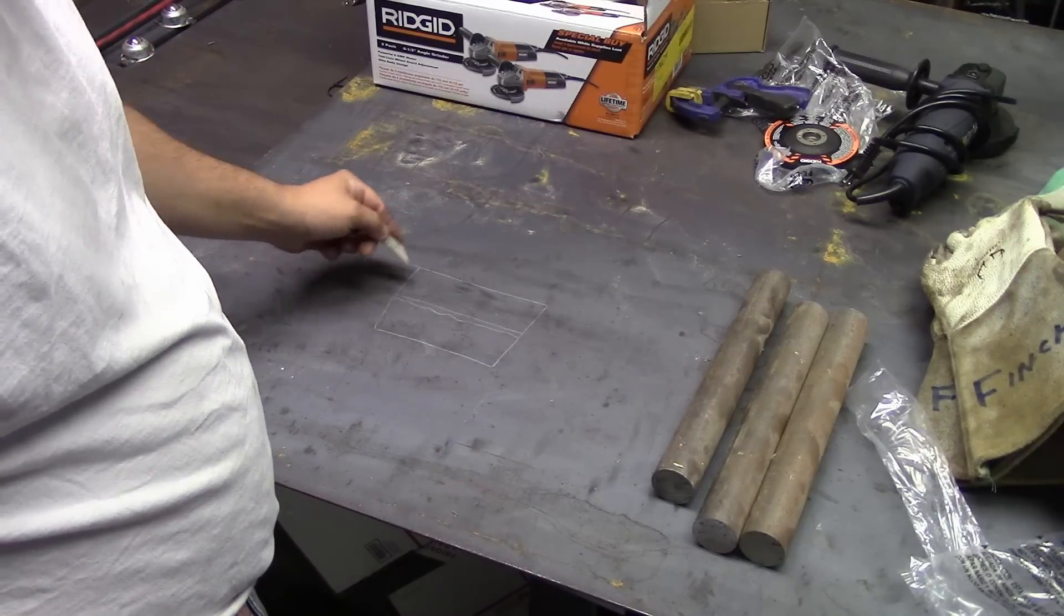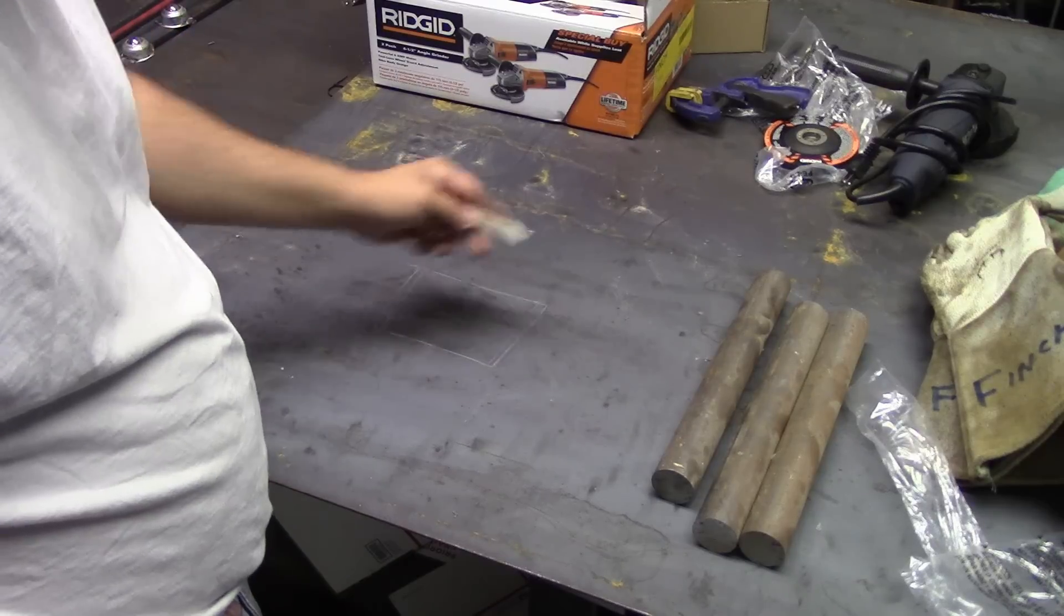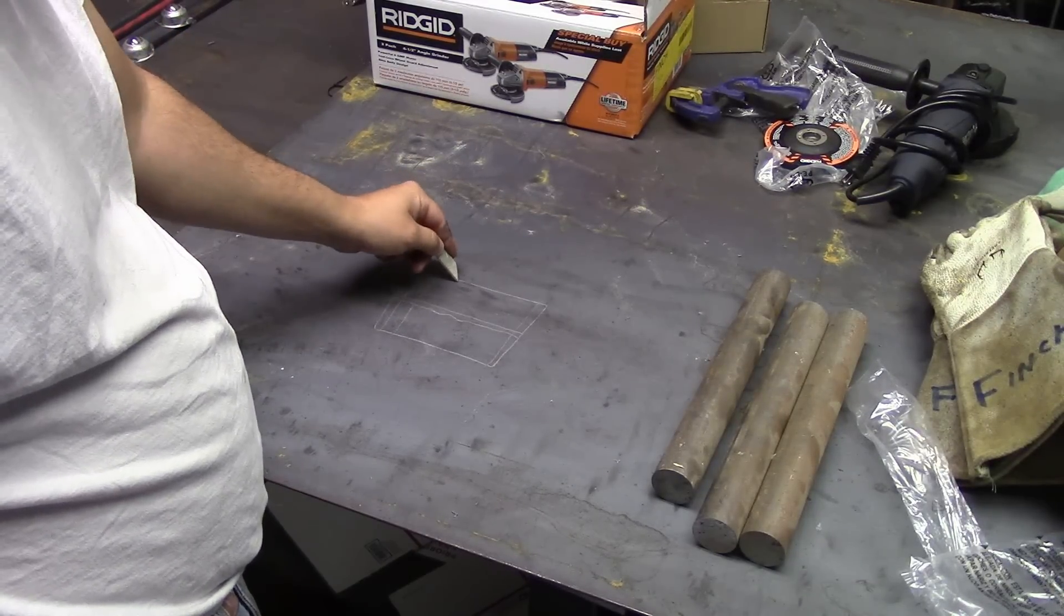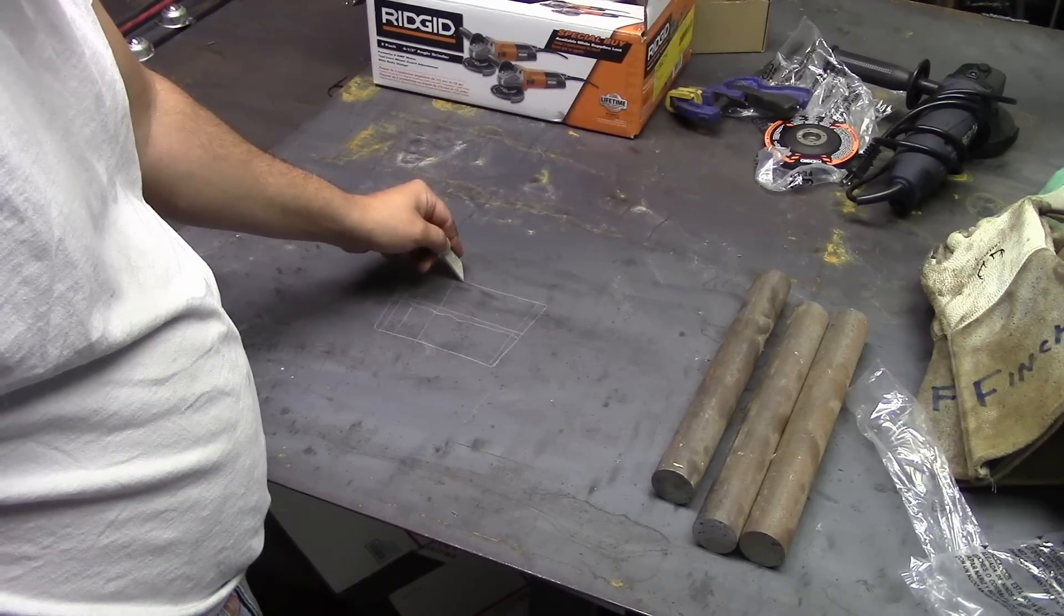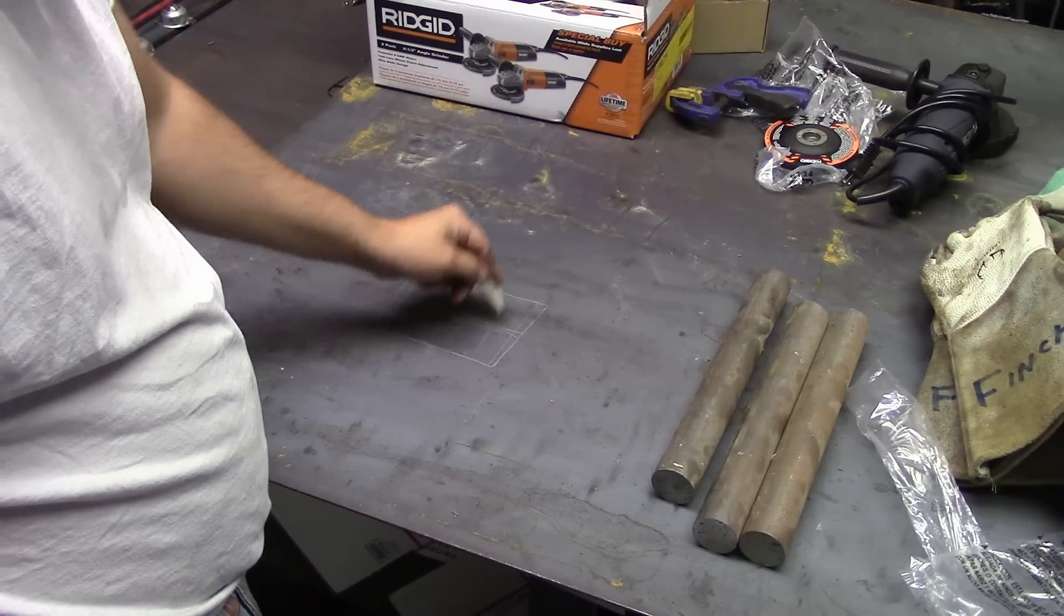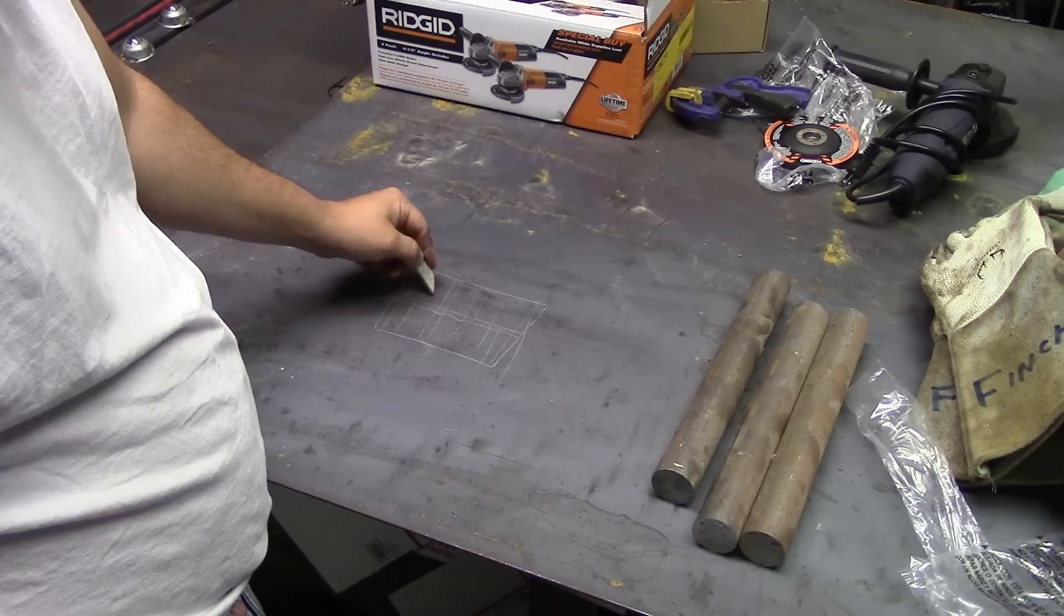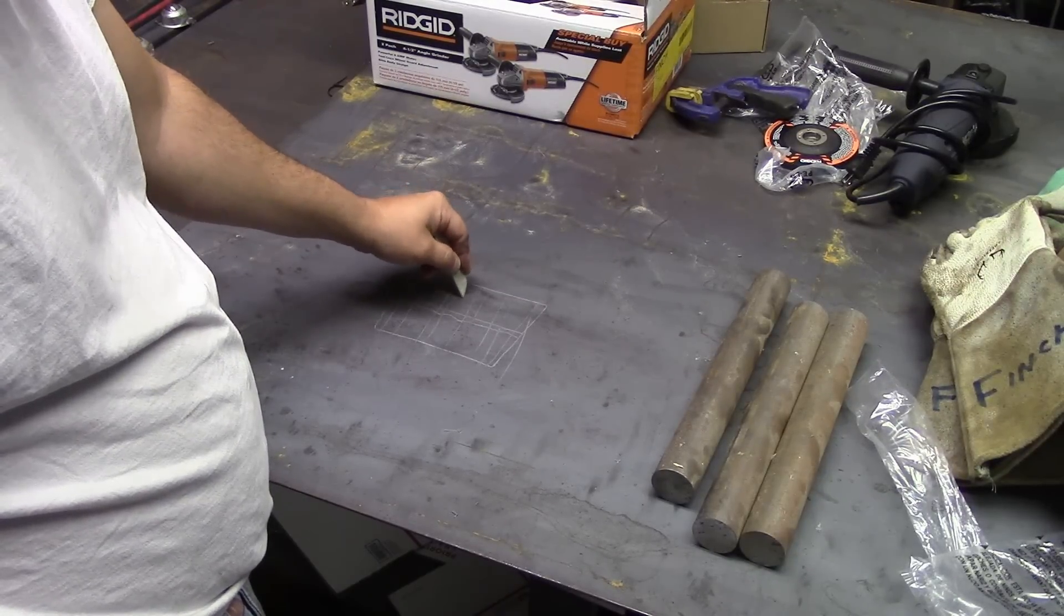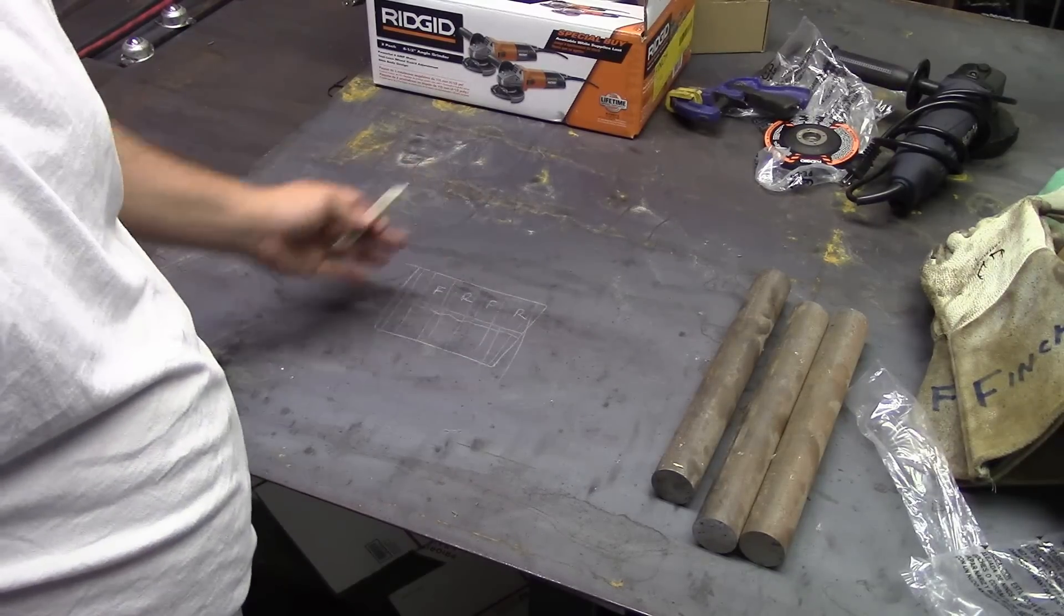So you did your weld, and they immediately discard these half inch ends. Then they'll take from here, they'll take a one and a half inch piece, they'll take another one and a half inch piece. So they take four of these one and a half inch pieces. One of them is your face bend, your root bend, face bend and root bend.